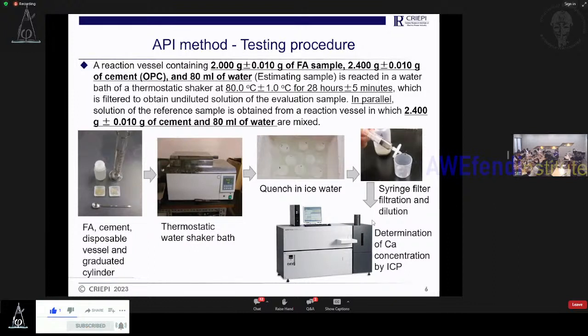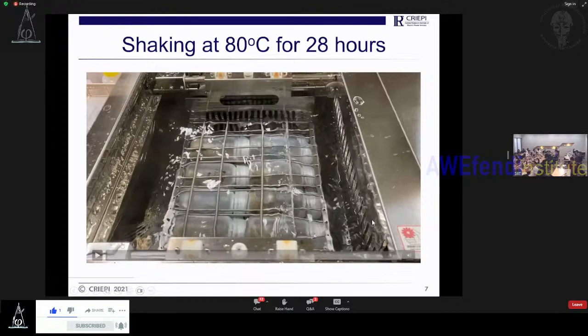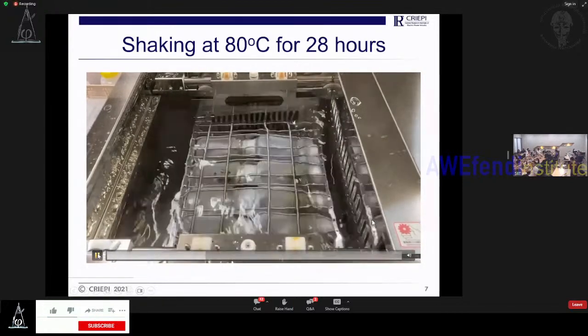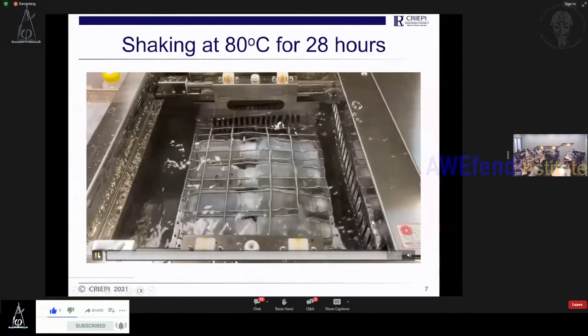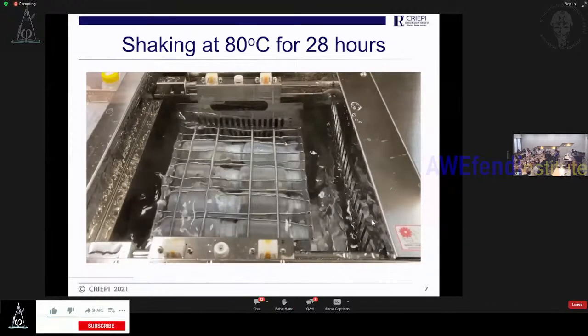We must keep it in the thermostatic water shaker bath, like shown in this picture. After 28 hours of curing, we take out the sample bottles and quench them in ice water. We need to cool down quickly. After that, we filter using syringe filters, and then dilute to a suitable condition for each equipment, like ICP. I'll show you a small movie like this. We shake it in 80 degrees hot water for 28 hours.